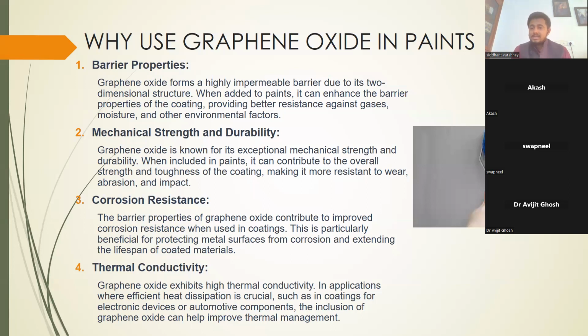So alkali resistance, chemical resistance, acid resistance, all these things are given by graphene. Corrosion resistance, it works wonders. It gives you a 1,000 hour salt spray result. In the salt spray test, generally 300 hours is the standard for approval into the anti-corrosion segment, but this goes for 1,000 hours, which is a very good milestone.